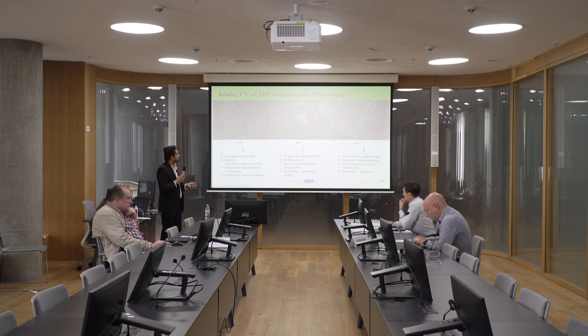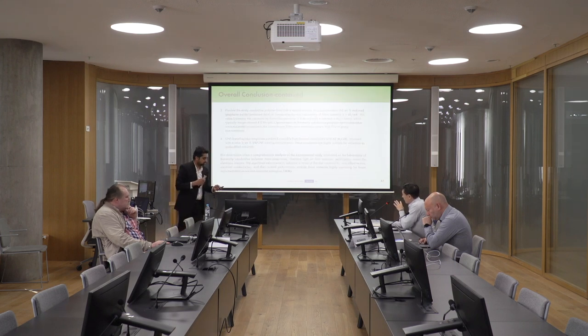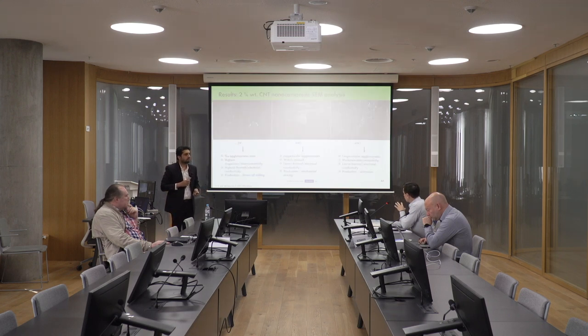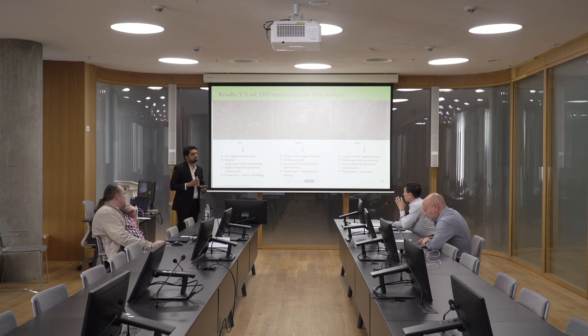So even though you say that you have these van der Waals forces, if you do not mix them well, with a homogeneous mix, because for the RDS system it is used from three roll mixing, then... So you say that you might have a problem with dispersion of carbon nanotubes, especially in multi-wall. I would expect the vice versa, because multi-wall carbon nanotubes are easy to disperse when compared to single wall. But in your case, I see it's a different result.